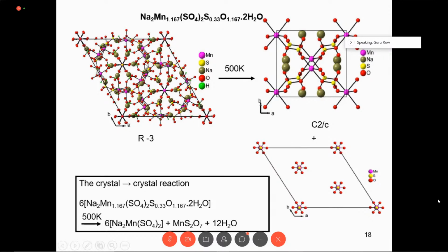This is the original crystal structure. It belongs to the space group R3 bar. We will not go into the detail of it. I'll say essentially that this structure has water molecules surrounding it, the green ones here. These water molecules get eliminated. The 2 water molecules go away at around 500 Kelvin. And there is a new phase, a single crystal phase, which is obtained with this particular structure.